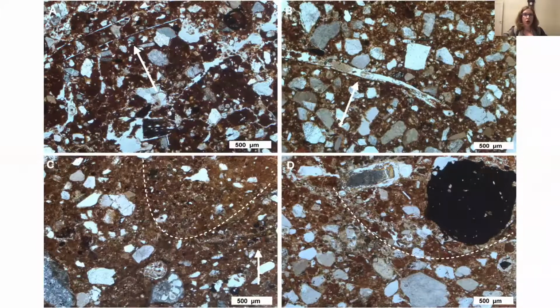The study of the petrographic fabrics, though, highlighted several other interesting aspects of Minoan manufacturing. First, the presence of different vegetal tempers is indicated by a different type of voids and impressions left by chaff and seagrasses. Voids left by seagrasses are usually wider and longer than the ones left by chaff. And you can see that even macroscopically, because usually chaff can be 2-3 centimeters long, whereas the seagrasses are from 10 to 15 centimeters long.